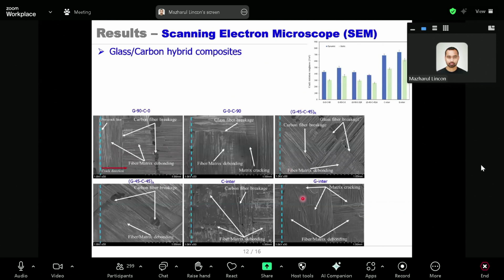The first one is interlaminar G90C0. Here, carbon fiber breakage is the predominant failure mechanism, and this carbon fiber breakage is actually the main reason for showing the high fracture toughness for this composite type.